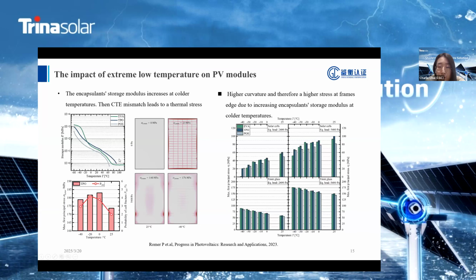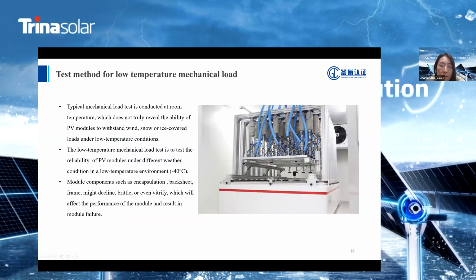Higher thermal stress due to CTE mismatch between front glass and frame results in a higher first principal stress within the glass at cooler temperatures. Thus, it's quite necessary to involve the influence of low temperature into the mechanical load test, although the international standards of it haven't been studied yet.